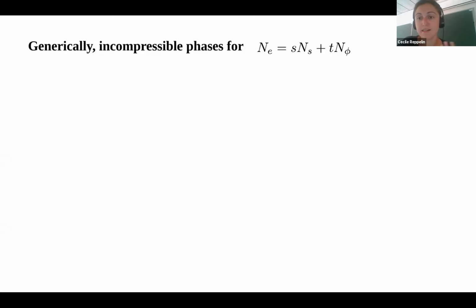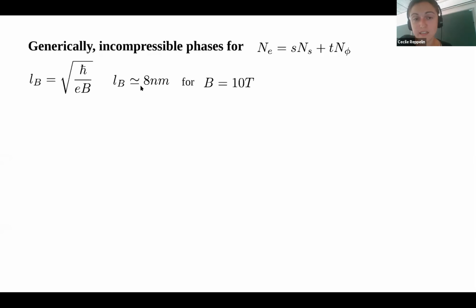To show that this approximation was indeed justified in the quantum Hall regime, I can just compute the typical value of the magnetic length for a typical magnetic field. Let's say 10 Tesla, which is already a very decent field. Then the magnetic length will be equal to 8 nanometers, which is much, much larger than the lattice constant for a typical lattice. For example, if you take single layer graphene and you wanted to have one flux quantum in every hexagon, you'd need a magnetic field of around 40,000 Tesla to reach this sort of order of magnitude, which is completely crazy and unfeasible, of course.